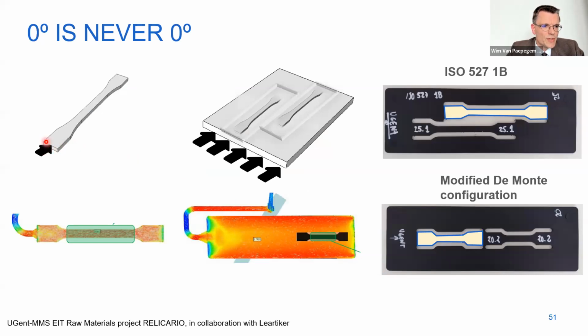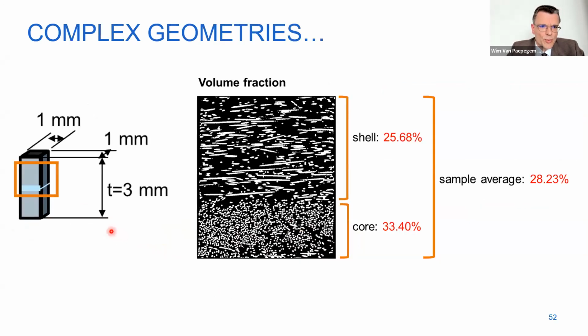If you inject a dog bone sample with short fiber, so directly into a mold with a dog bone shape, or you make a plate injection molded and then you cut your samples. And then you can even choose where you cut your samples, close to the injection gate or further away, or if you take longer samples or shorter samples. But here you see mold flow simulations from Leartiker, where we work together in a European project. And there you can see that fiber orientation is never 0. And indeed, I can prove you in more detail.